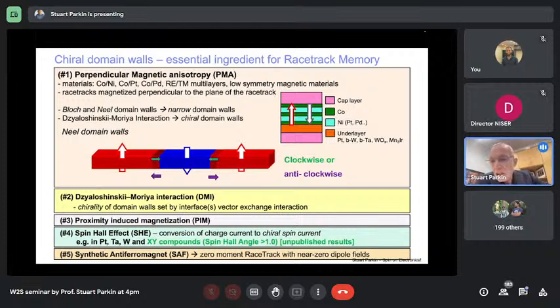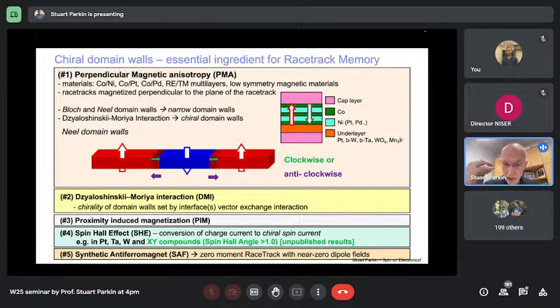I mentioned already that proximity-induced magnetization in these layers is very important, and recently we have some very exciting results published in Nature Materials, where we demonstrated not only can we make platinum magnetic by proximity to, in that case, YIG, which is a soft magnetic, ferrimagnetic insulating garnet, but we also demonstrated we can make platinum superconducting by proximity to a conventional superconductor like niobium, and we demonstrated for the first time a Josephson diode effect through platinum when it is magnetized by proximity to YIG. If we switch the direction of the magnetization, we switch the direction of this so-called Josephson diode effect.